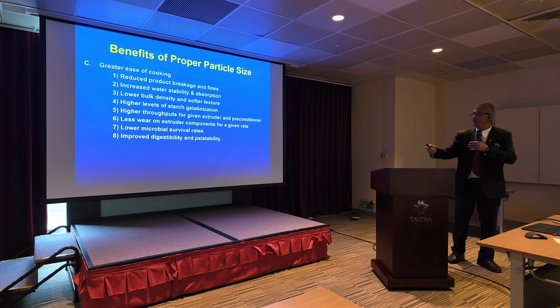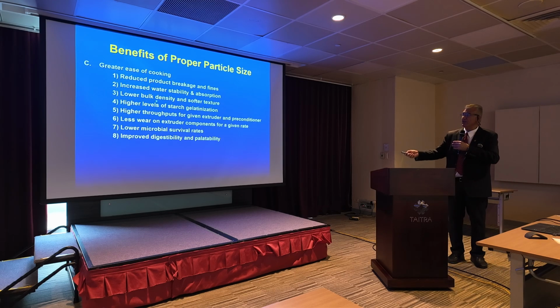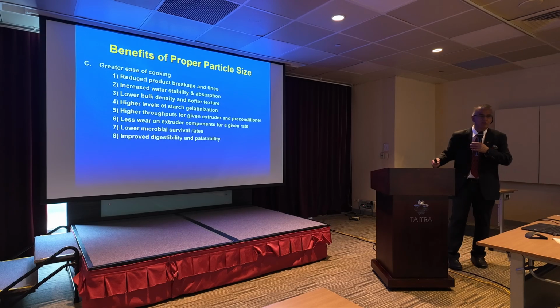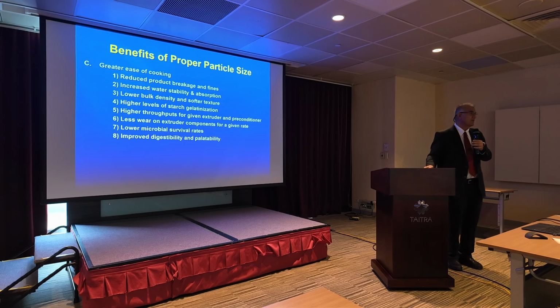Also, with that, you can increase water stability, lower density, softer texture, higher level of starch cooking, higher throughput, less wear and tear in the extruder, low microbial survival rate, and improved digestibility. These are just some of the benefits you get from proper grind size.